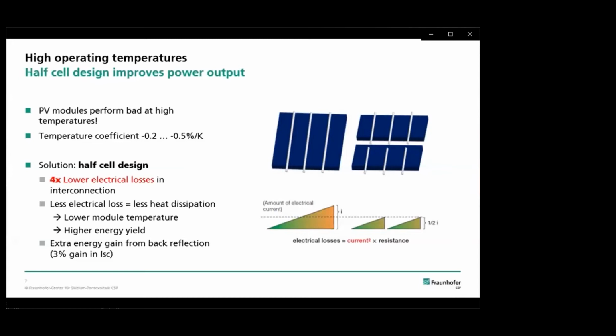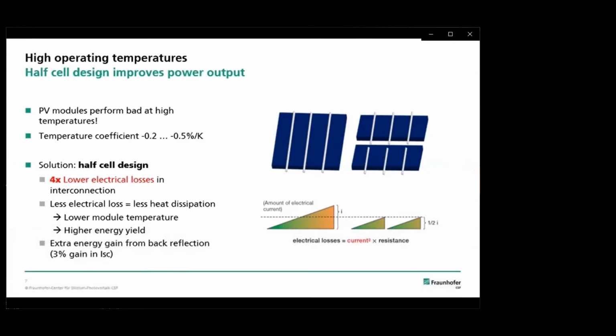A potential solution to that could be, for example, the adoption of half-cell design, as shown here. On the right side, you can see a solar cell which was cut in half, and due to that, we will get much less electrical losses in the interconnections, which is due to the fact that this depends on the square of the current, which then will be halved because we cut the cells in the center.